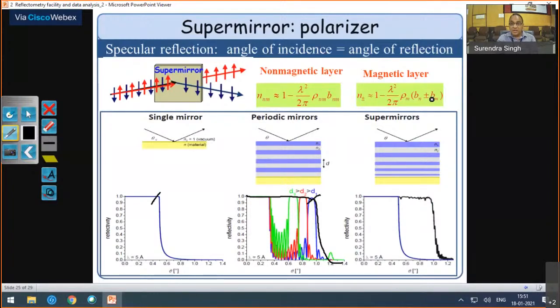If you choose it such that this becomes equal to the non-magnetic part of the material, then the spin down component won't see any change in refractive index, so it will transmit. Basically, that's what you are engineering.